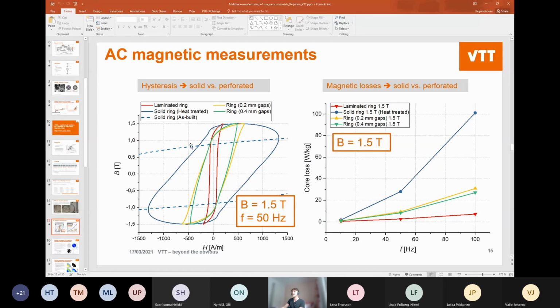And the dashed line is the printed material without heat treatment at all, which was bad enough that it doesn't even fit the scale here. The coercivity was really high due to the fact that you have a lot of grain boundaries in the material, as Olli was showing in the first presentation, which is inherent to the laser powder bed fusion process. But with heat treatment you can improve the properties, and with a clever design you can improve further. But we are still not quite there as with the conventional material.